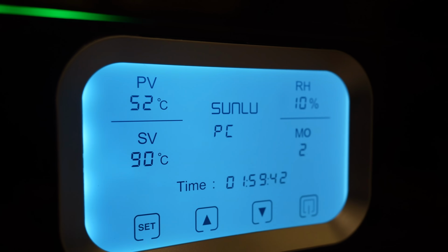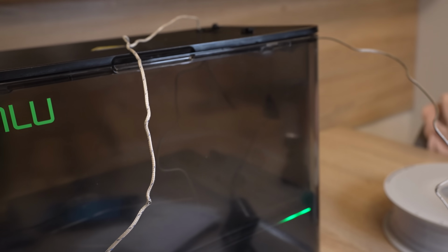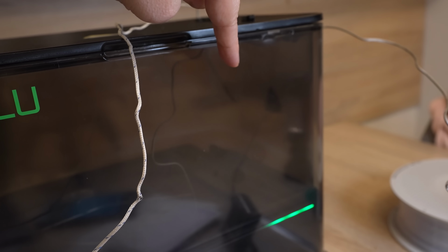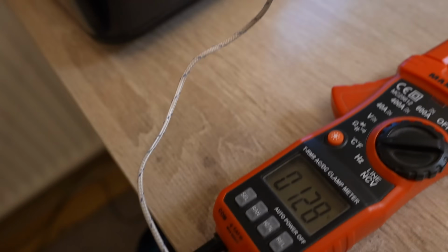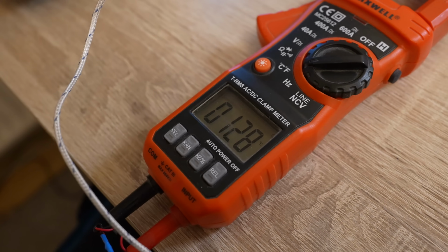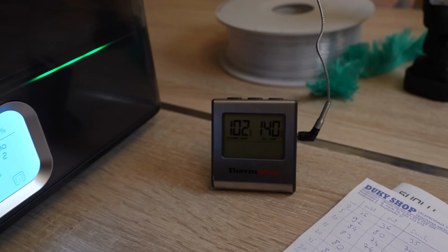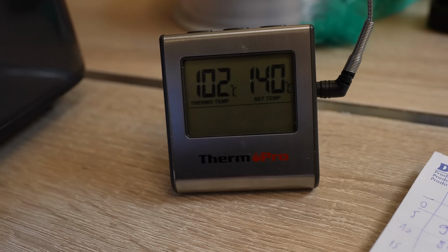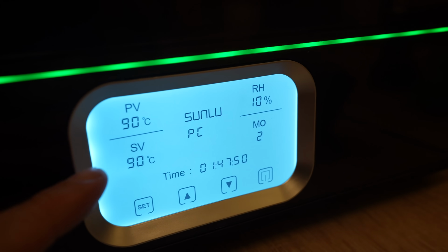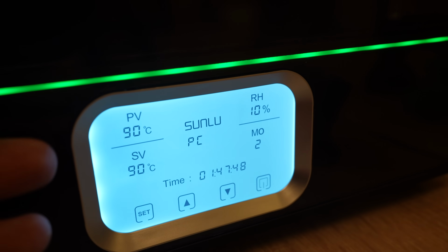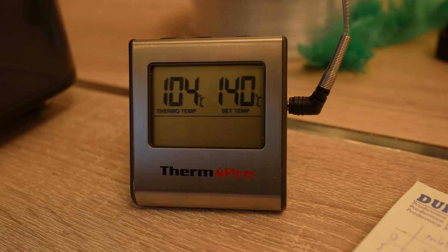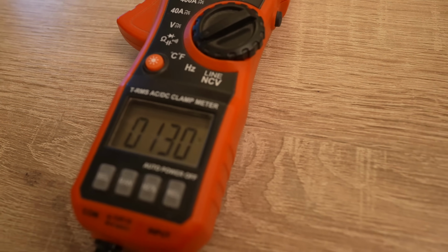Mode 2, 90 degrees Celsius. Only after 10 minutes I started to measure the hot air temperature 2, which is currently 128 degrees Celsius. And the annealing temperature is 102. After 12 minutes it reached 90 degrees Celsius, and probably now the temperature will stabilize. The annealing temperature is 104 degrees Celsius, and the hot air temperature is 130 degrees Celsius.